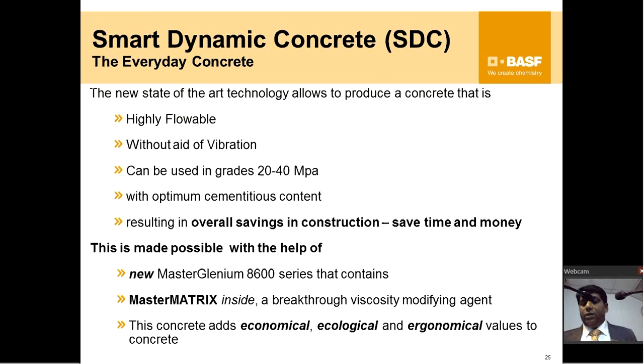Now, years back when the actual concreting was being done, when we did self-compacting concrete, even for an M30 grade, there was a very high amount of cementitious content, to the extent of something like above 500, 600 or sometimes even 700. When you have a very high cementitious content, your strength achieved is above M50. So it was way too expensive and way too QC sensitive for it to be used for an M30 grade. You always land up getting an M50 mix.